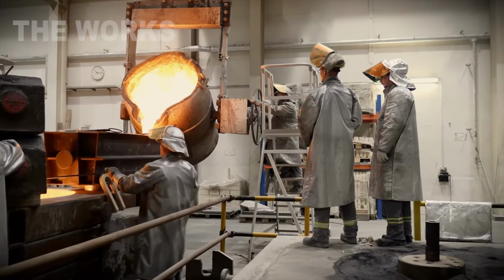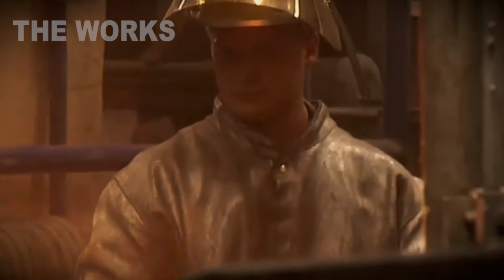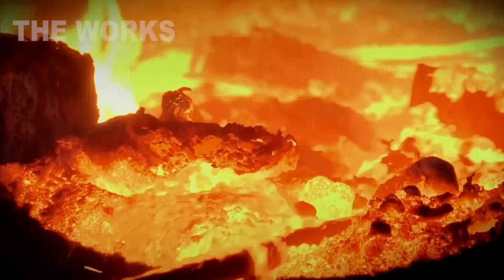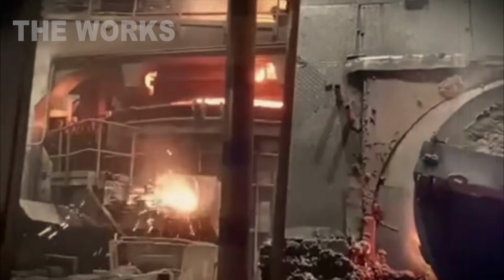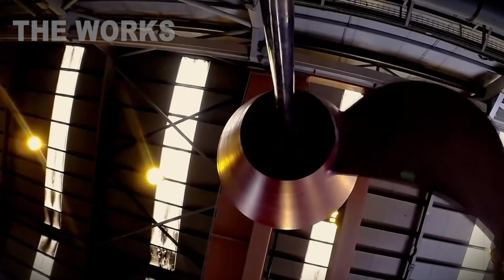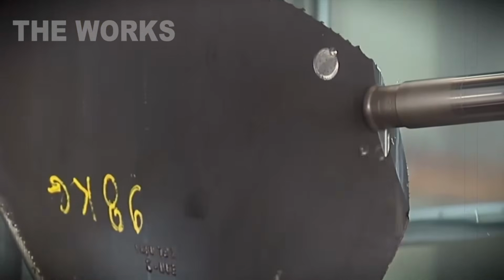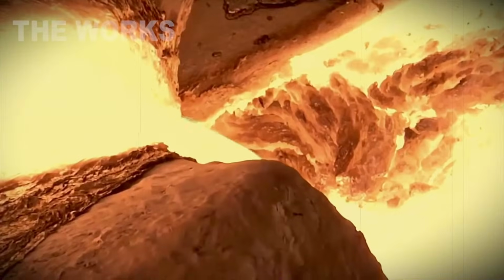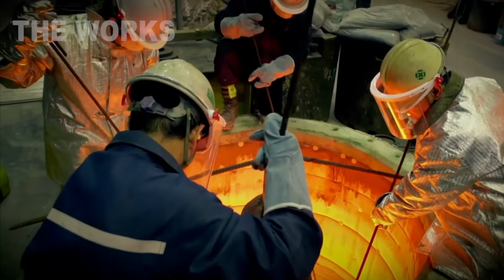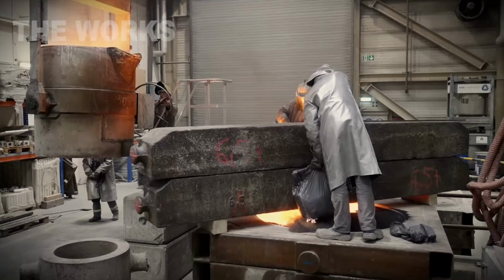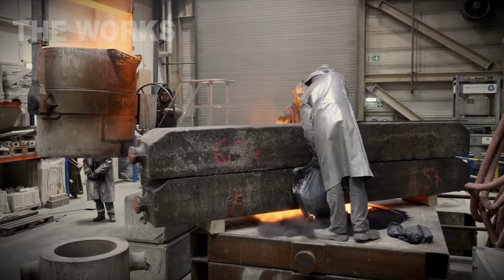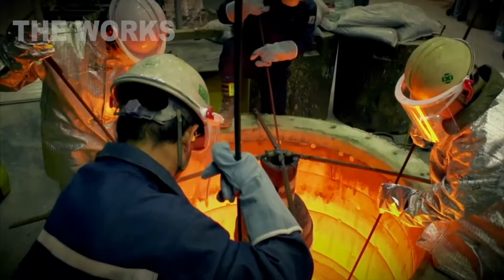And all this massive metal at a temperature of around 2,000 degrees Fahrenheit has to get into the mold evenly, no pauses, no stops. The metal is melted in large induction or arc furnaces. Depending on the plant's configuration, there might be several of these furnaces, and they run in parallel to accumulate the necessary volume of molten metal by the time of pouring. When the metal hits the right temperature, lab techs take a sample, a small portion of the melt, and send it for rapid chemical analysis. If the element ratios check out, they greenlight the pour. If something's off, they adjust it right there in the furnace, adding whatever element is needed, then take another sample.